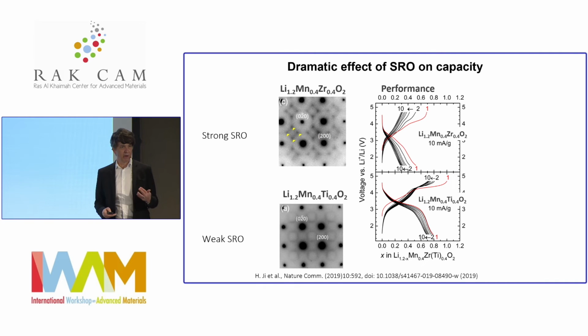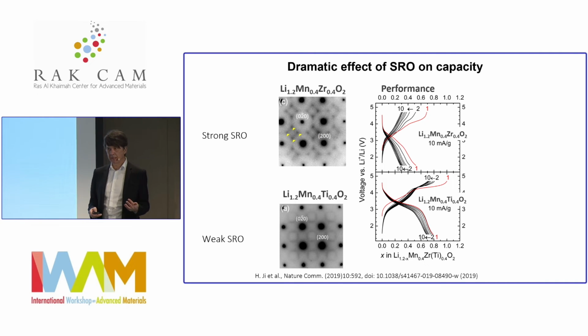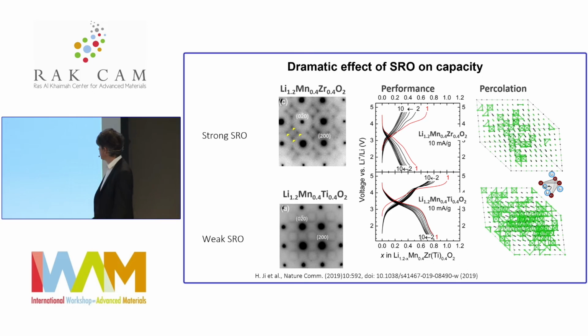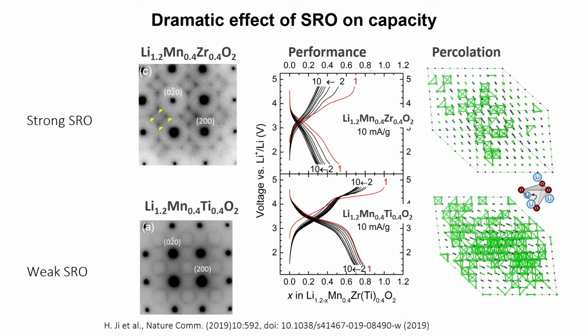So these are materials that are almost the same, except they differ in their short-range order, and if you look at ab initio simulations, this is the percolation network in the titanium one, and this is the percolation network in the zirconium one. As you see, this is much more pronounced. Here, disorder has destroyed almost completely your percolation network. So this is something we had to learn to deal with, because short-range order is not that easy to quantify, and especially not in diffraction techniques.